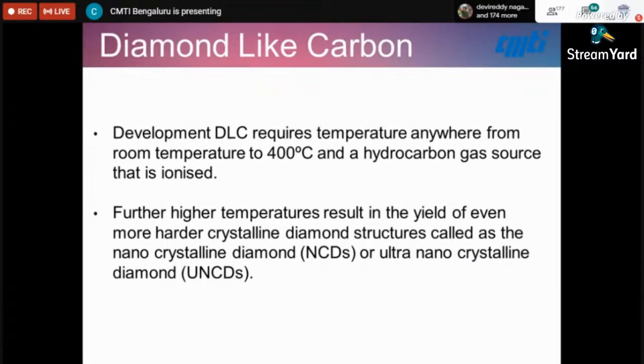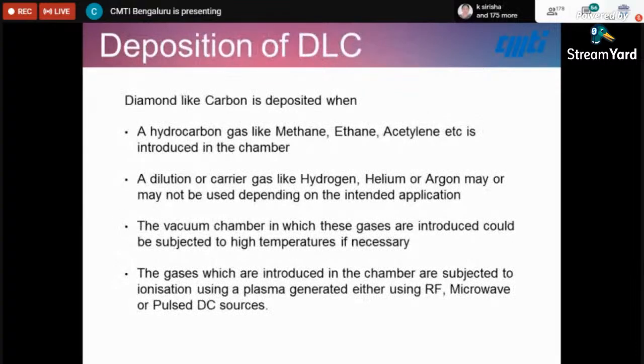Typically, DLC requires temperature anywhere between room temperature and 400 degrees centigrade, and you need to use a hydrocarbon gas source, which is ionized. At higher temperatures, you would get a yield of harder crystalline diamond structures called nanocrystalline diamonds or ultra nanocrystalline diamond. So how do you deposit DLC? Now this is the most important part of this presentation. You can choose a hydrocarbon gas, let's say methane, ethane, or acetylene, and introduce it in the chamber. Then you require a carrier gas or a dilution gas, hydrogen, helium, or argon. We prefer hydrogen, with methane as the hydrocarbon gas, either methane or acetylene.